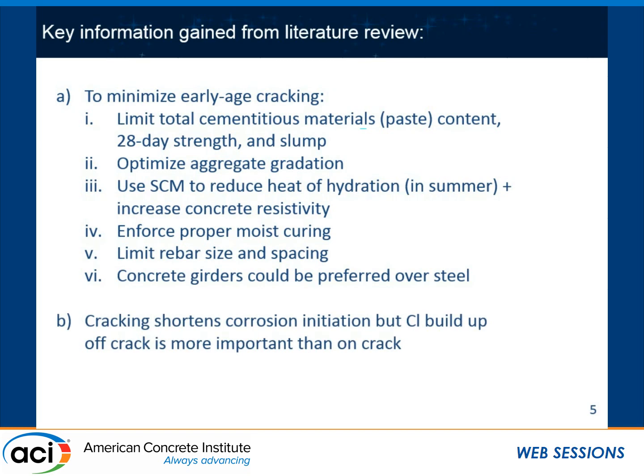It makes sense. You get cracks, the salts can get direct access to the rebar. But it's interesting that chloride buildup off the crack seemed to be more important than on the crack. The reason suggested is that right at the crack you can get some corrosion and corrosion products which effectively seal the crack, or at least seal the tip of the crack right where it intersects the rebar. And it seems like until the other parts of the rebar start active corrosion, you don't get a lot of corrosion happening.